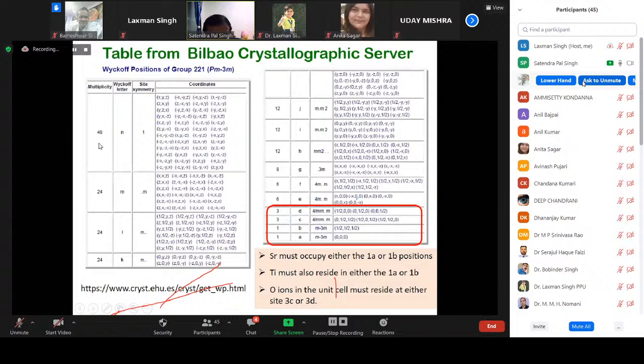So we have to look at which sites we can put those atoms. If you go on screening these things, you will find that we have 1 atom here, so if I put it here we get 1 atom. So 1a, and here is also 1b. So which site to put? And then oxygen, the 3 is here, so it can be at the 3c site or 3d site. So there are 2 choices. We can put strontium at 1a or 1b, and titanium at 1a or 1b.